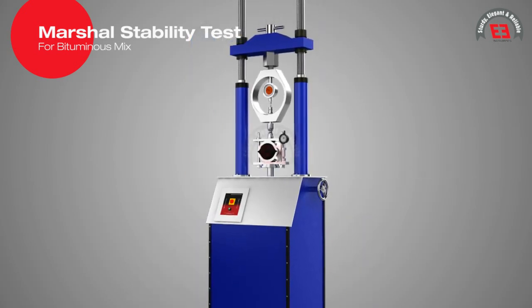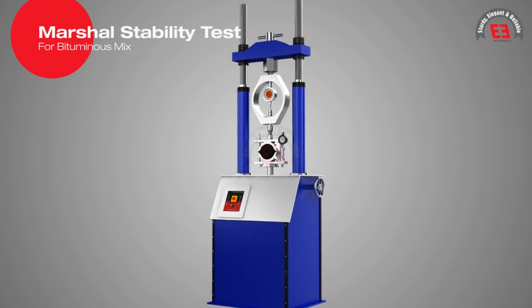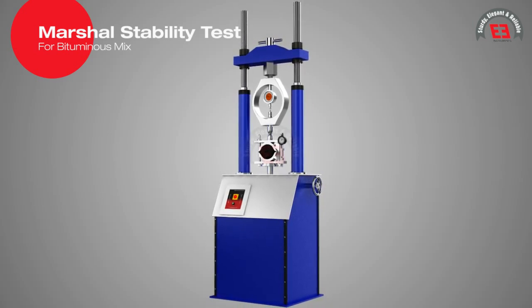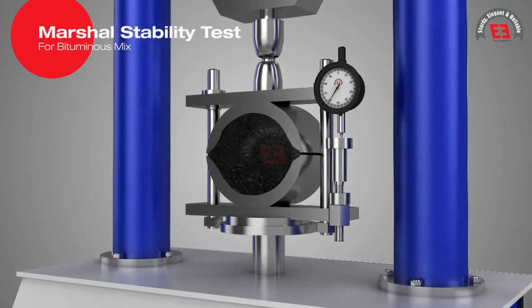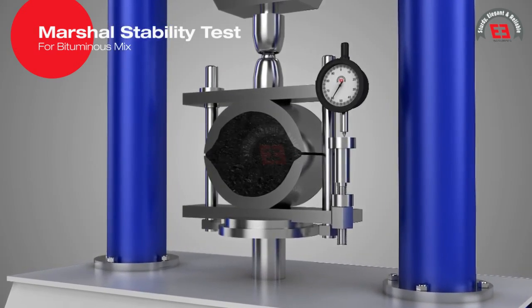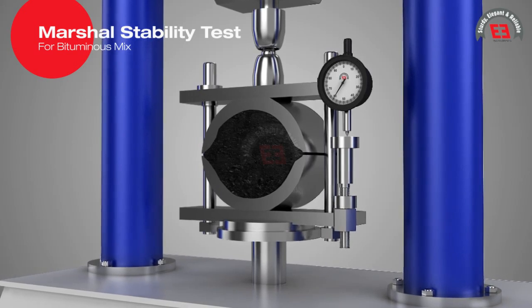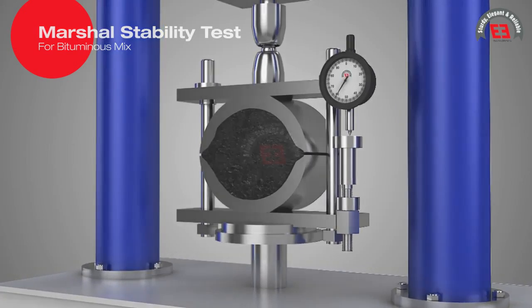The Marshall stability of the bituminous mix specimen is defined as the maximum load carried, in kg, by a cylindrical specimen of bituminous mix under specified condition of temperature, that is 60 degrees Celsius.